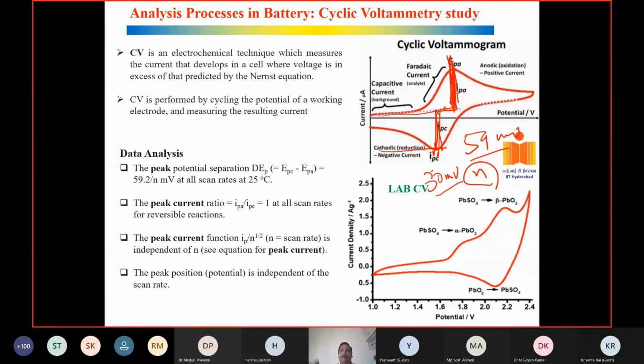So you can understand what oxidation and reduction are happening, and accordingly you can set a cutoff voltage. After the oxidation you can stop the reaction. Maybe sometimes you will see a plateau, and after this position you can stop the reaction, correct? That means no more charge is being accepted by the cell. That gives you the cutoff voltage of the cell. So these are the things we do.